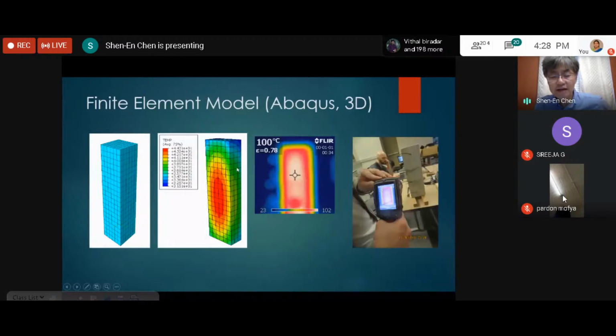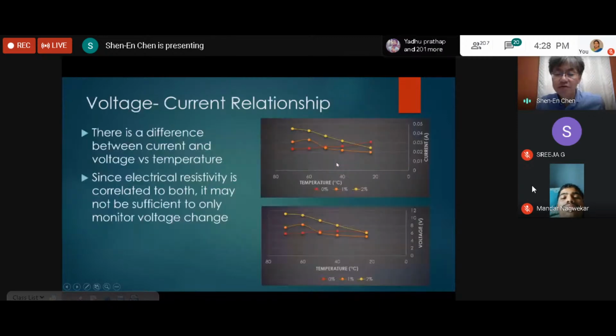But the general idea is that the surface of the material is cooling at room temperature. And so you have a hot core, and then you have a cooling surface surrounding the hot core material. And this red spot here is actually where we have the strain gauge and all the epoxy. So that has a different cooling effect on the element. So we understand that what we're measuring is accurate.